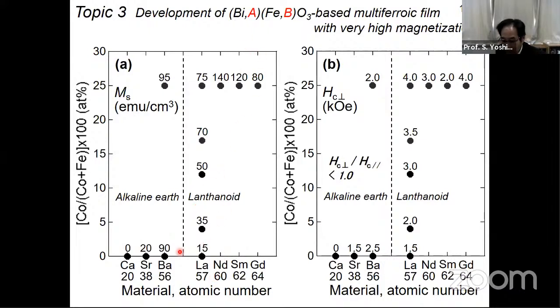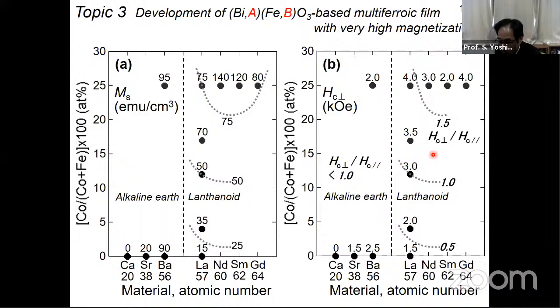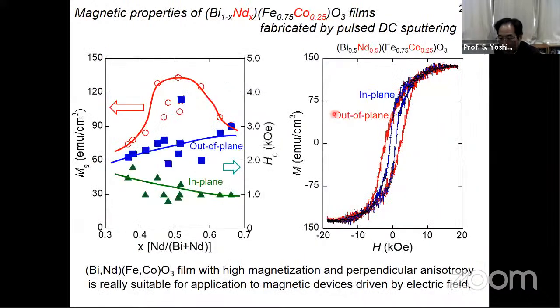I discussed many materials for the substitution. A site here and B site here. In the case of neodymium, very high saturation magnetization was obtained. And also, this material has large coercivity in the perpendicular plane. And also, the magnetic anisotropy is very high. So, okay, this material has a very large saturation magnetization with perpendicular anisotropy. So this material is suitable for application to magnetic devices driven by electric field.